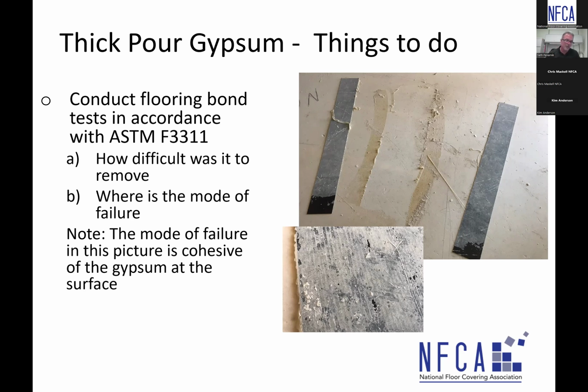And you take a putty knife and you kind of go underneath the flooring to separate the bond, and then you grab the flooring with your finger or maybe a pair of pliers, and you slowly and evenly pull it directly towards the ceiling in as best of a 90-degree angle to the substrate as possible. I know it's tough, but you slowly pull that up very consistently in a very equal, slow speed, pulling it directly up towards the ceiling, and then you evaluate the mode of failure. And with your waterborne adhesives, you should commonly see failure within the adhesive.